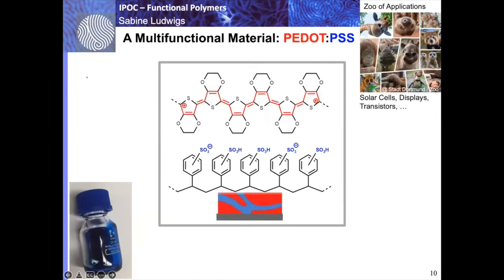A very interesting material, which is additionally also commercial, which makes some of the applications easier, is this so-called PEDOT:PSS. If you look again at the top structure, the red one, that's very similar to the chemical structure I've just shown before. So that's also a polythiophene in its highly doped form, together with a polystyrene sulfonate, also a chemical structure I've shown before, that's a polyelectrolyte. This combination, a blend, you can buy as an aqueous dispersion. If you deposit that on a surface and make films of that, it self-assembles into domains which contain the electronic conducting polymer and the ionic conducting polymers.